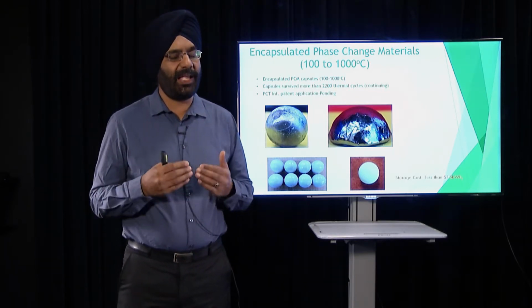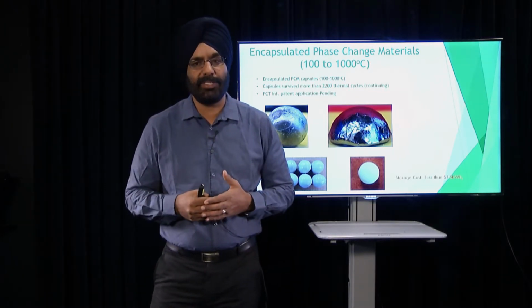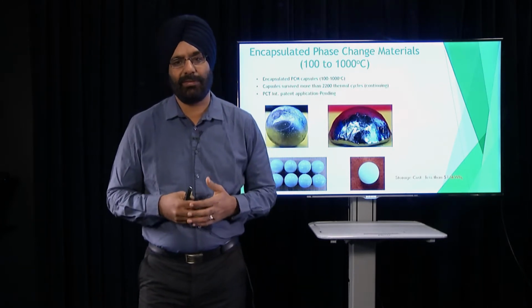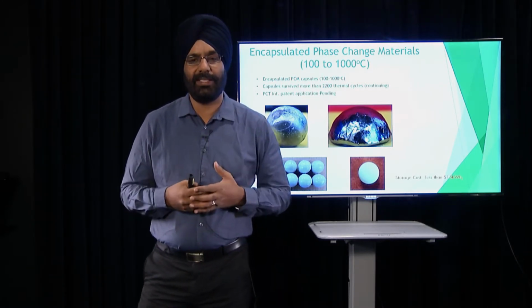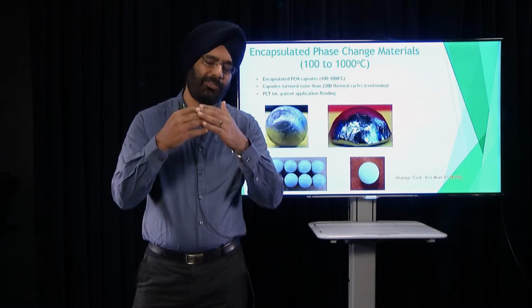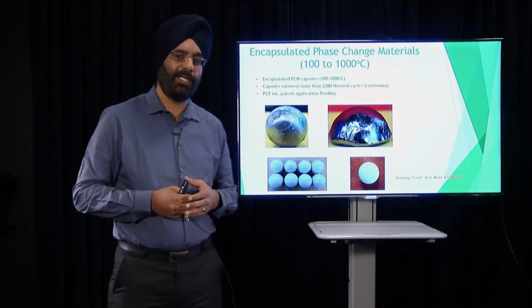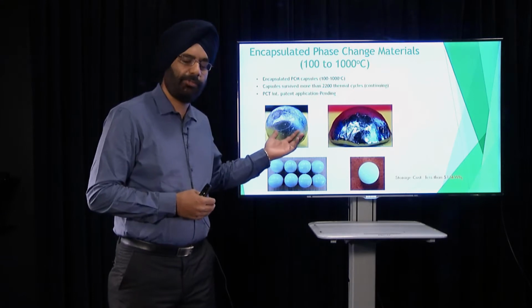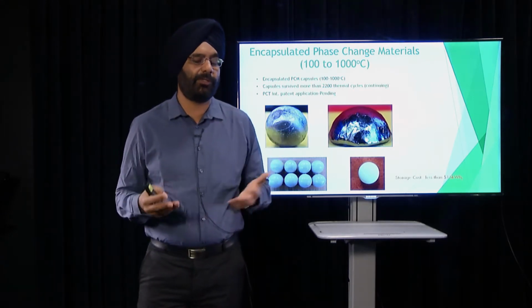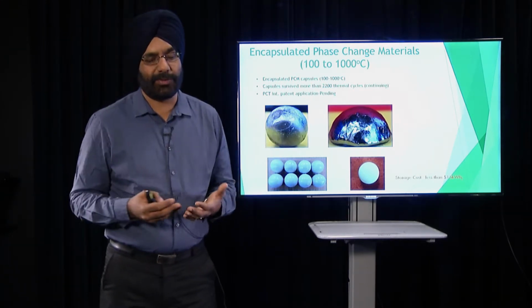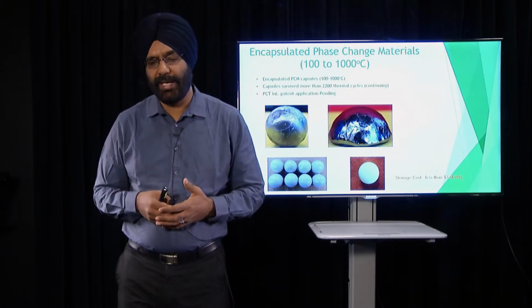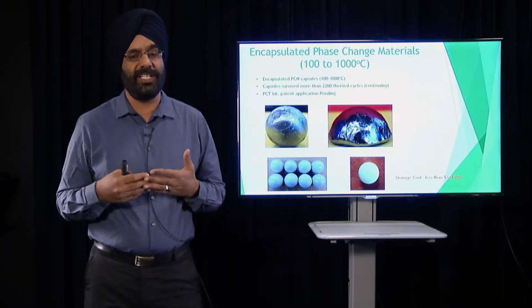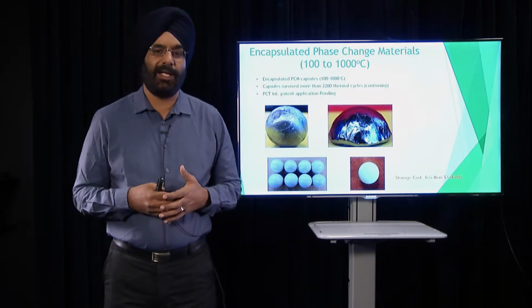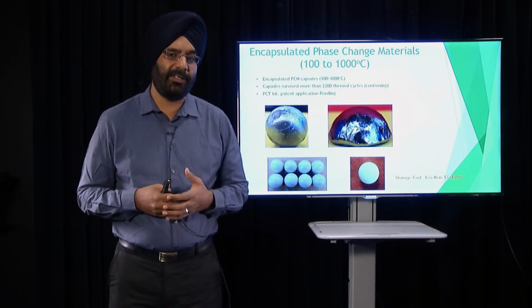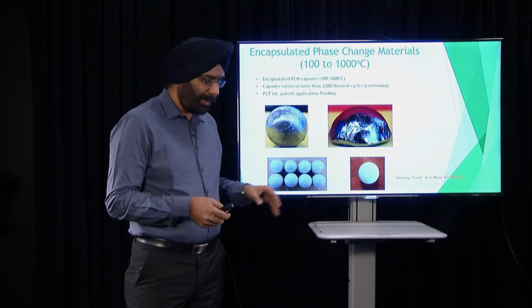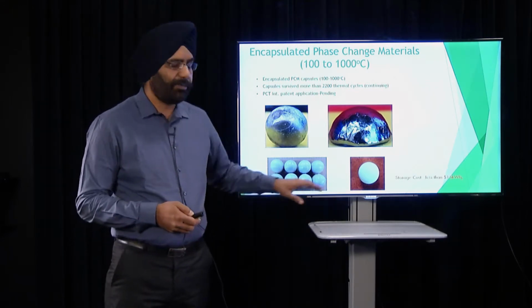The reason is, as you go higher in temperature, the efficiency of generating electricity increases. So the target is to go to as high a temperature as possible. If that's the case, then you cannot use polymer, you cannot use metal, because they corrode. So the only material which is left to encapsulate the phase change material which melts at high temperature, say 800, 900 degrees C, is ceramics. So we have also developed some ceramic capsules.